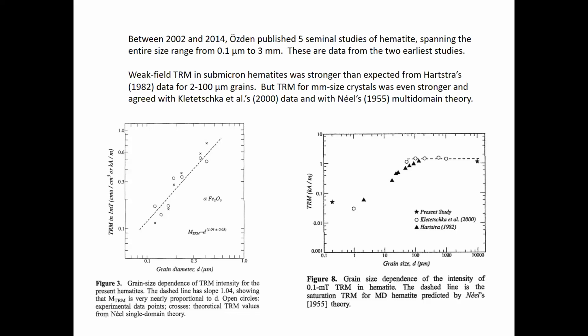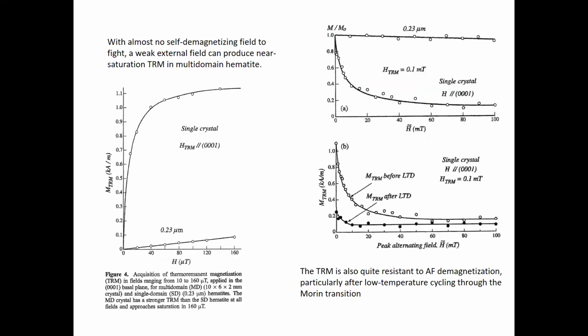So these are just some of Özden's data in the submicron range, and also she looked at single crystals. Everything is nicely compatible, both with Néel's single domain theory, which magnetite never is, and Néel's multi-domain theory, the dashed line on the right. So how can you produce this large TRM in a mineral which by definition is weakly magnetic, 200 times weaker than magnetite? This seems very counterintuitive. Well, that very weakness means that there's virtually no internally magnetizing field in hematite. And therefore, by applying a field of 50 microteslas, something like the Earth's field, you are practically at saturation. You are making use of the saturation magnetization of hematite. So that's why it works.